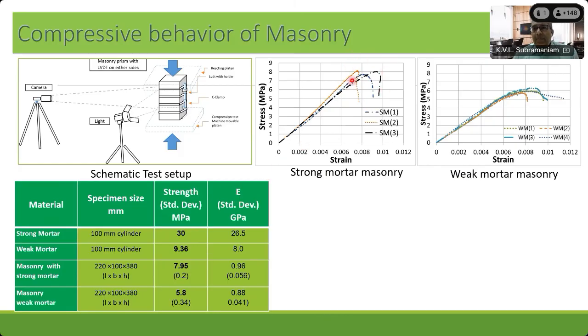What we find is that the compressive strength of the masonry, this is the compressive behavior of the masonry, is actually lesser than the compressive strength of both the brick and the mortar. This comes as a surprise because normally when you work with composite theory, the composite would have a strength which is somewhere in between the two constituent materials. But what we find here is that the compressive strength of the masonry is actually much lesser than the compressive strengths of the two materials that were used.